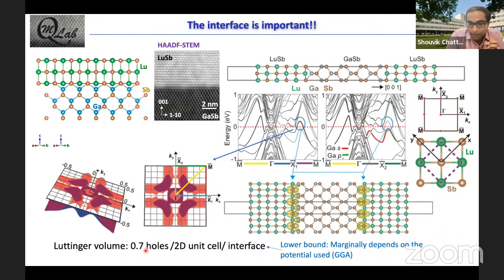per interface. I want to highlight here, though, that these slab calculations were done using the GGA potential, which is not exactly accurate. What we had previously done for the bulk was at HSE, but then it becomes too expensive. So the number here, you should take it as a lower bound for what we expect in this material system.